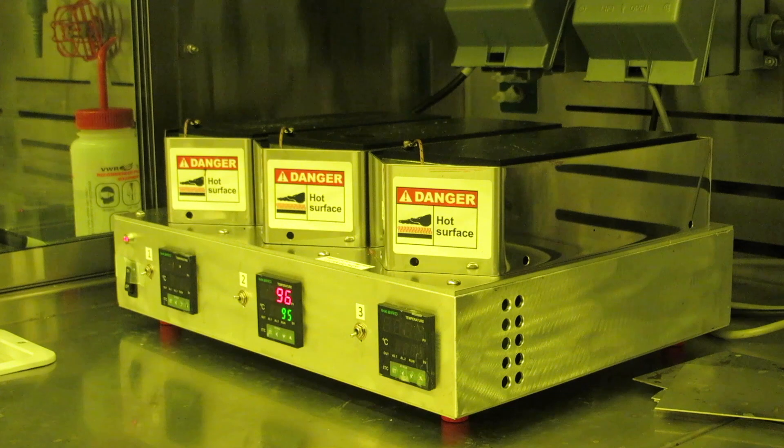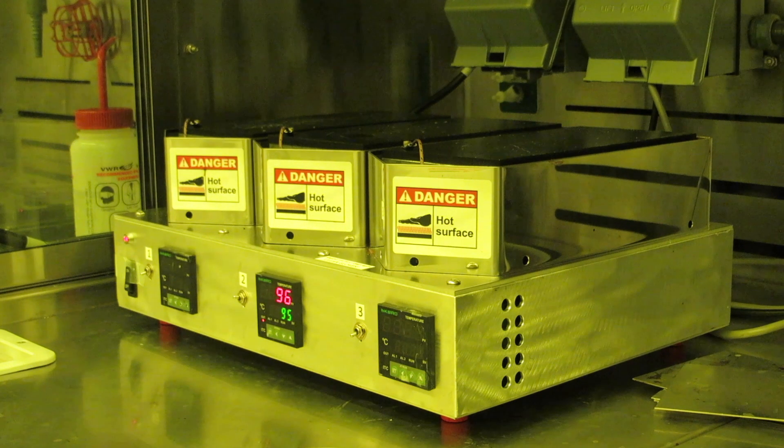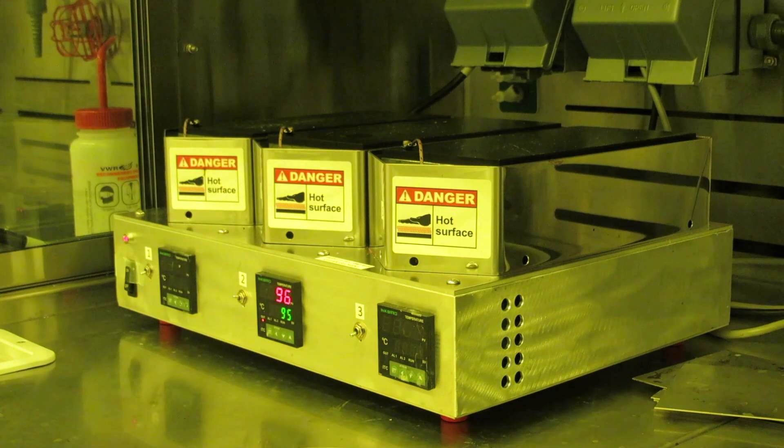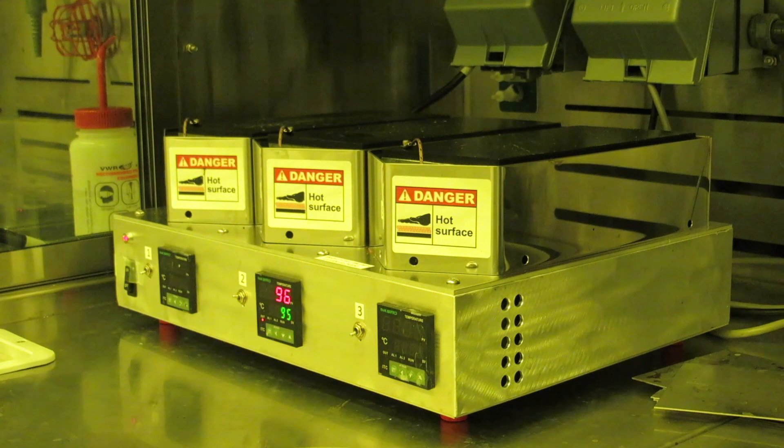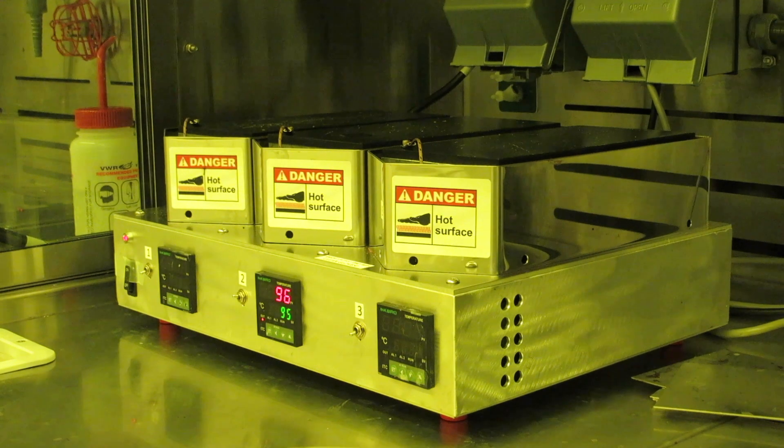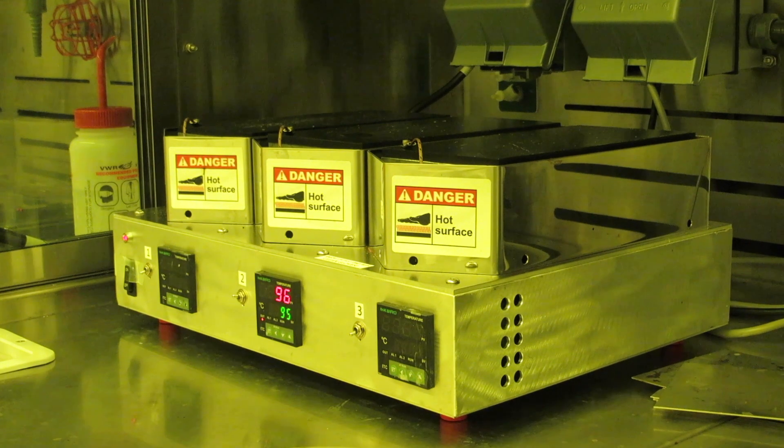You can use higher temperatures, but they must be shorter. If you heat it at too high of a temperature for too long, you can damage the photosensitive compounds in the resist, and you can also eventually cross-link the resist which will make it impossible to work with.